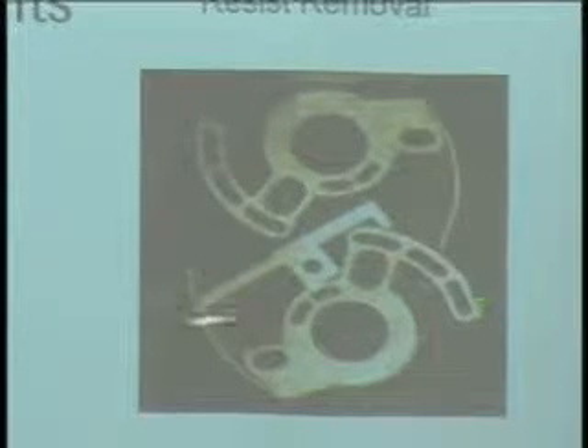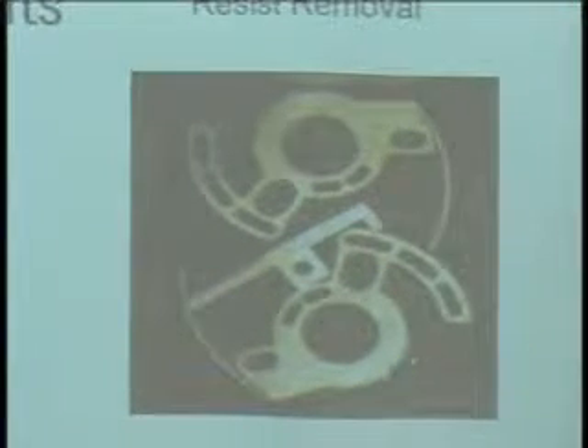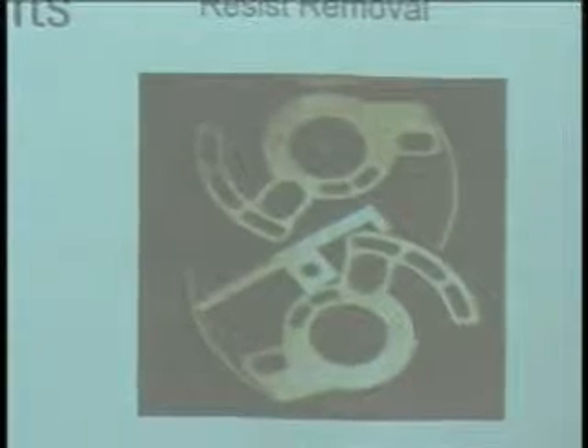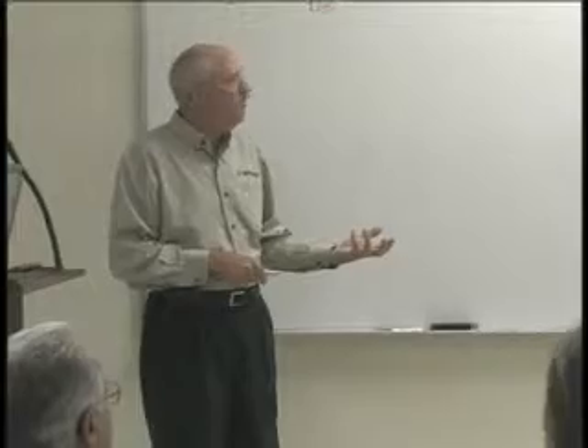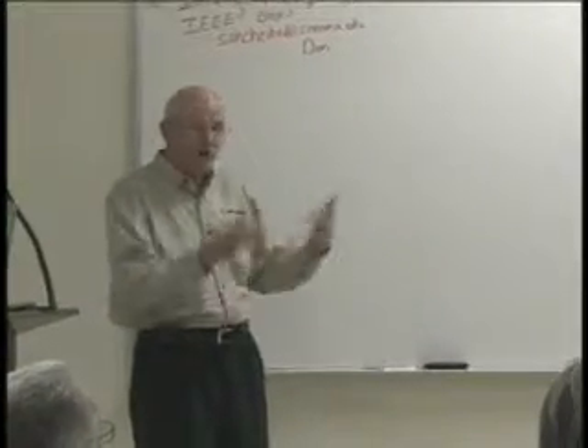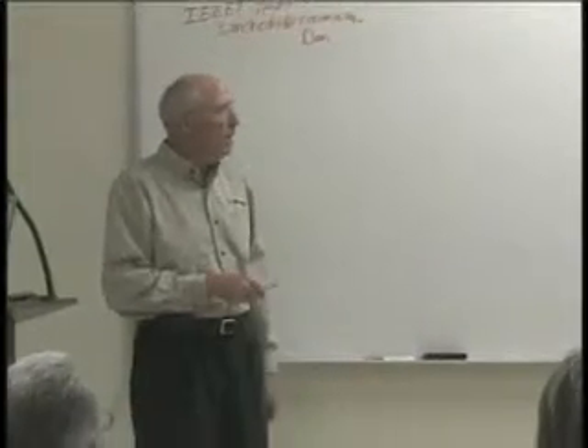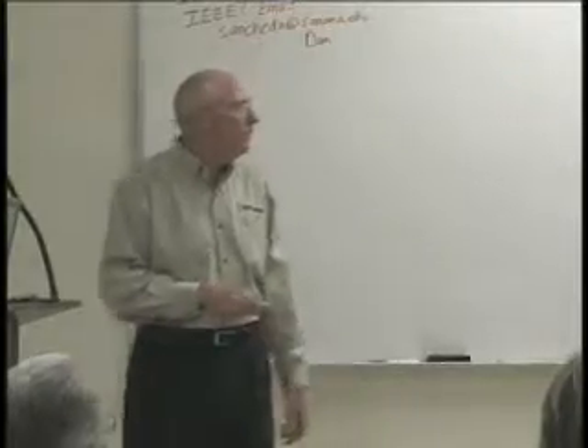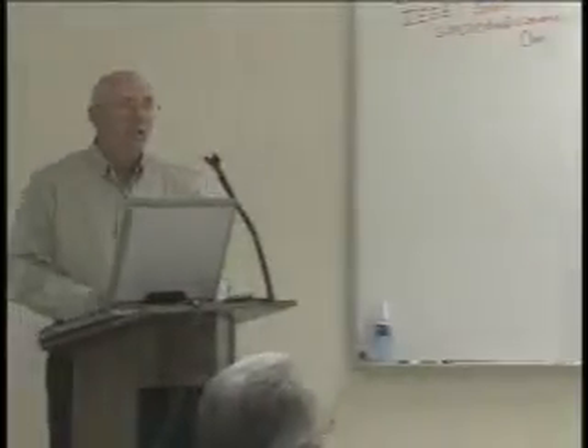These gears are, and I don't have a micron bar, but they're probably on the order of about 100 microns across, and you can see these little tiny gear teeth. They're really small. And this was done with LIGA. So you produce a three-dimensional metal structure as your component, or you actually produce a mold insert that you can then use to inject such things as metals, polymers, glasses, or ceramics to make other kinds of components. It's really good for very high aspect ratio microstructures, and it's a relatively inexpensive process.